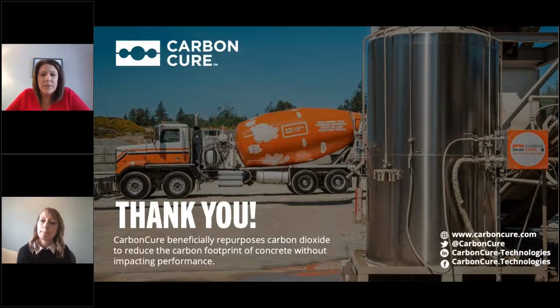Yeah, I'll just answer all of it and maybe throw some more in. As mentioned, that chemical reaction takes place with the cement alone. So we can absolutely use CarbonCure with slag, fly ash, SCMs. There is no impact. The CO2 itself is dosed on only the amount of cement that's in the mix. And then when we get further into implementation and we talk about reductions, we incorporate total cementitious into some of those calculations and those values.